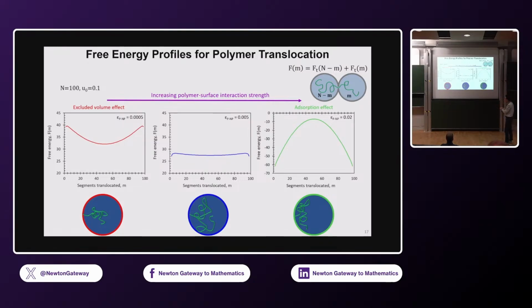So when you have very weak interaction between the polymer and the surface, what the polymer wants to do is maximize the volume that it takes up. Okay, so when the polymer has half of its segments in the second pore and the other half in the first pore, you have the lowest energy state, so that you see a big energy well there. When the polymer is very sticky to the surface of the pore, what the polymer wants to do is minimize the volume that it spreads itself in while sticking to the surface. So the polymer would rather stay in one pore, so that's why you see this big energy minima when the polymer is completely in one pore, one cavity or the other cavity. Okay? So somewhere in between, you have this free energy profile where it's fairly flat.